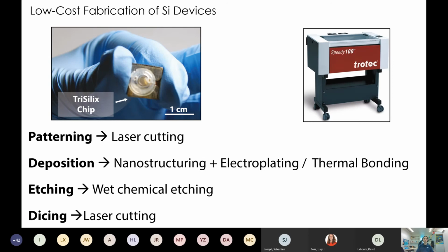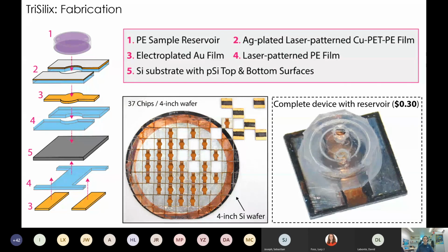So here we show on the left-hand side one of the devices that we have produced. This is the TriSilix chip with the reservoir on the top. As you see, it's a small device that intends to replace the large tabletop devices for PCR detection. And the process is a batch process. That means that we can use a whole wafer, which is just a silicon wafer. With a single wafer, we can make up to 37 chips, and this is a 4-inch wafer. We can make the wafers bigger, which brings the cost down to approximately 30 cents per device.